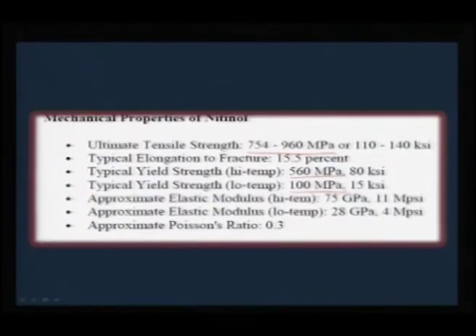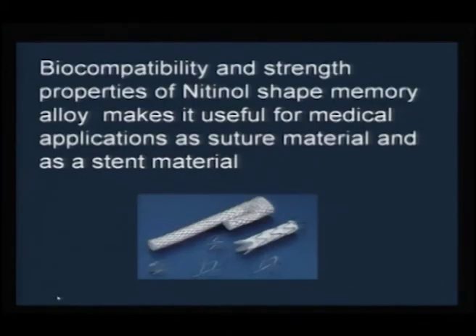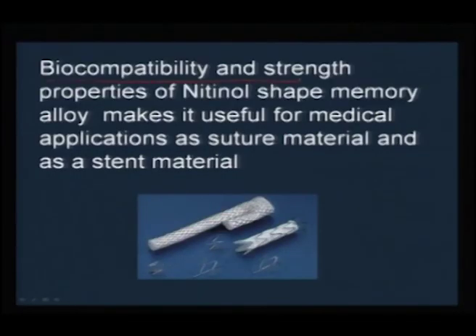Therefore, you should know under what tensile strength this shape memory alloy effect can be used. And similarly, you have the elastic modulus at low temperature and high temperature, which is 75 and 28 gigapascal. So, this is quite a good amount of detail which can help us devise nitinol for several device applications. The most important property of this shape memory alloy is biocompatibility if we want to think about biological applications. One of the usefulness of the biocompatibility and strength properties of nitinol is to use this in sutures and also as a stent material.